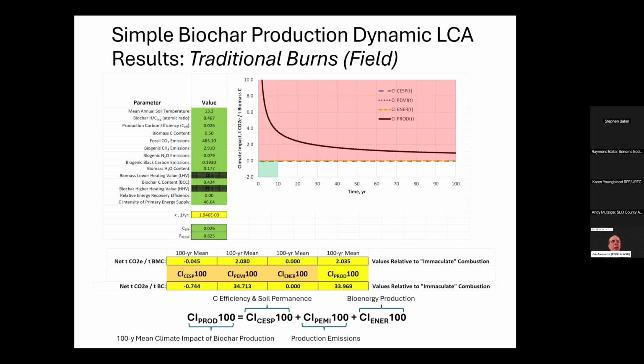We look at the quality of the biochar, which is the atomic ratio. In this case, for this one, it was about 0.47 hydrogen to carbon. That's a little on the high side, but it's well within the range of what we consider normal biochar, which is say from 0.1 up to about 0.7. The other thing we consider is the carbon efficiency, which I showed you some data for previously. In this particular one, it's about 2.5%, meaning that 2.5% of the carbon in the biomass ended up in the char or the ash at the end of the burn. Biomass carbon content is 0.5.